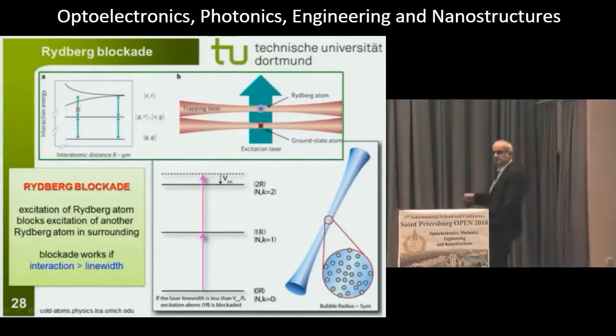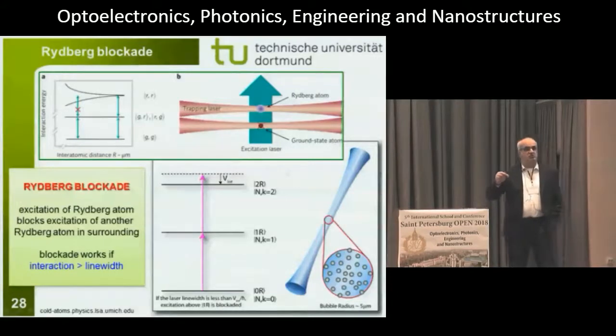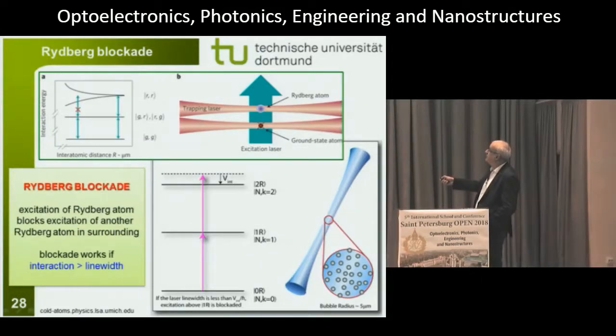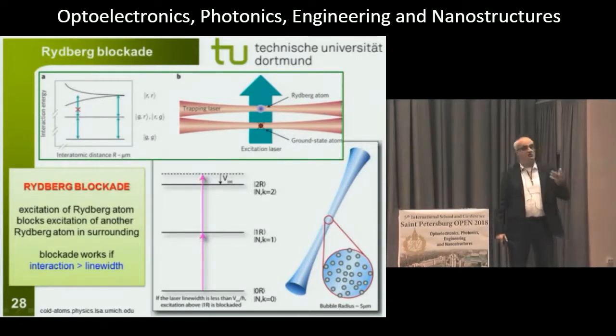And then you want to repeat this step. You want to take the very same resonant laser and excite a second atom into such a Rydberg state. And this is no longer possible because of the huge interactions that these atoms show. Once you have one atom in a Rydberg state and you want to excite a second atom, due to the interaction of these two resonances, the resonant line is strongly shifted out of the resonance profile of your laser. So for such a cloud, you can excite one atom into a Rydberg state, and a second excitation is not possible. This means that by exciting only one atom into a Rydberg state, your whole cloud of atoms has become transparent. So it's really a switching on a quantum level.